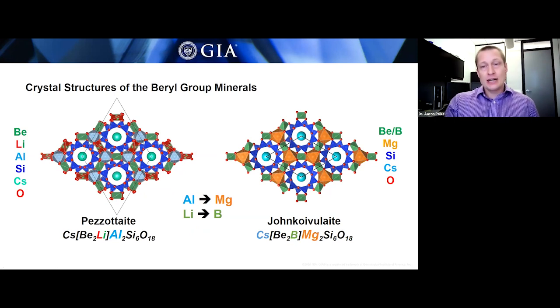Now, pezzottaite's actually kind of similar to johnkoivulaite in terms of the complexity of its chemical formula and its differences from beryl. We see with pezzottaite, we're substituting aluminum for magnesium in johnkoivulaite, and we're substituting lithium on one of these distorted tetrahedral sites for the boron in johnkoivulaite. And what you'll see in pezzottaite, these distorted tetrahedral sites actually get split into distinct crystallographic positions, or crystallographic sites. And so you see this site is split. We have these green distorted tetrahedra, and we have the red distorted tetrahedra.